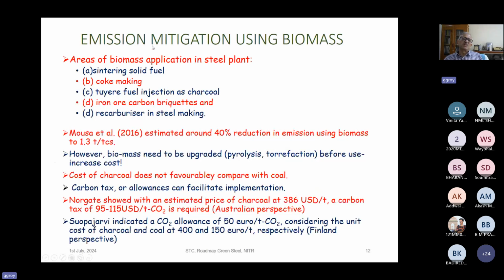Emission mitigation using biomass: the areas of biomass application in the steel plant. Already biomass is there at the research level, and also some implementation. It has come very slowly, but at the research level it is there. So biomass has been applied as sintering solid fuel. That is, during sintering we use coke breeze, so we can replace the coke breeze by biochar and then produce the sinter. And it has been found that there is a limitation, because the sinter quality deteriorates beyond a certain replacement of the coke breeze by the biochar.